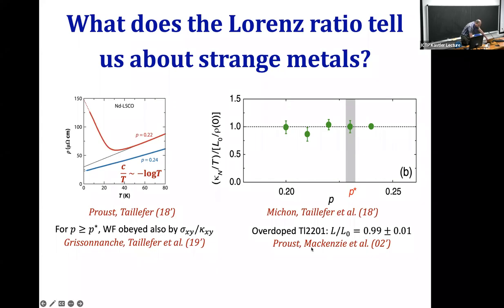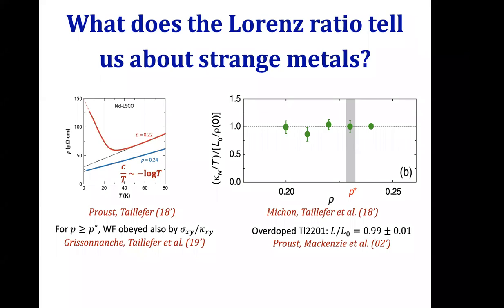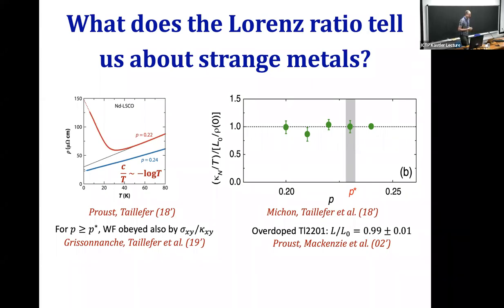What's the temperature here? Upper figure, right? This one temperature, right? Yeah, so this is trying to extrapolate to T equals zero. So they measure the Lorenz ratio. Superconductivity is suppressed by high field, and this is trying to go to the lowest temperature. Because really the Wiedemann-Franz law should only be obeyed, even in a normal metal, only at zero temperature, right? Right, yeah, so that's the question. So presumably it is an impurity dominated regime.